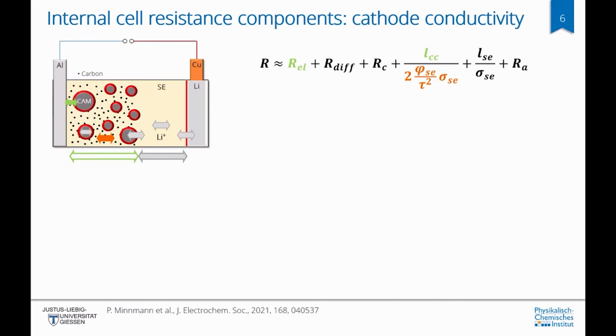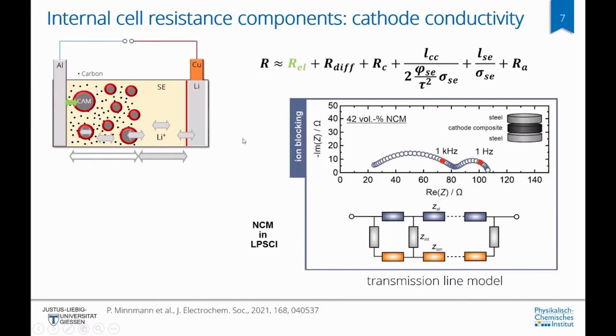However, the picture is quite different when we go to the cathode composite. Here we have several aspects to look at. One is the ionic conduction through the thiophosphate solid electrolyte, and the other is the electronic conduction to the current collector for electron transport through the cathode active material or a carbon additive. In order to investigate this, Philipp Minnmann from our group has investigated a cathode composite between two stainless steel current collectors, which are ion blocking, and therefore solely investigate the electronic conductivity of the composite cathode.